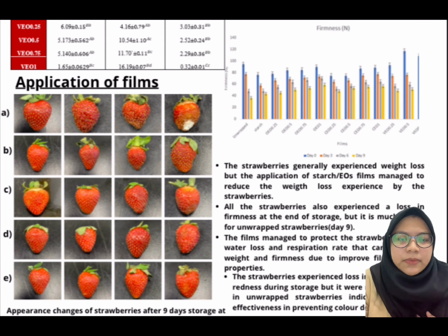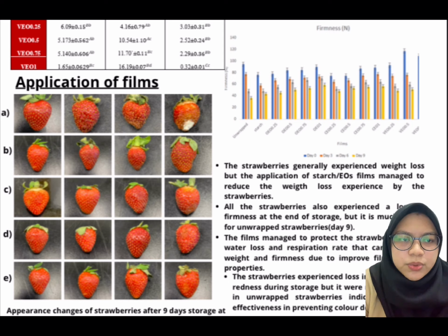Finally, for the film application on the strawberries, the strawberries generally experience weight loss, but the application of the starch with essential oil film managed to reduce the weight loss experienced by the strawberries. And as you can see here in the graph, all the strawberries also experienced a loss in firmness at the end of the storage, but it is much higher for unwrapped strawberries compared to wrapped strawberries. It concludes that the film managed to protect the strawberries from water loss and respiration rate, maintaining their weight and firmness due to the improved film's barrier properties.